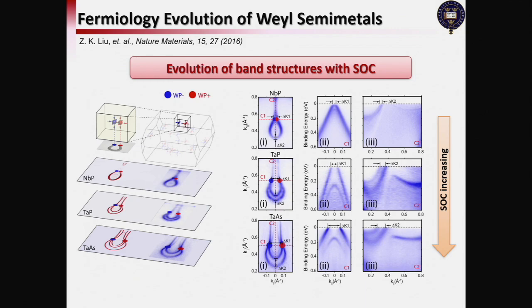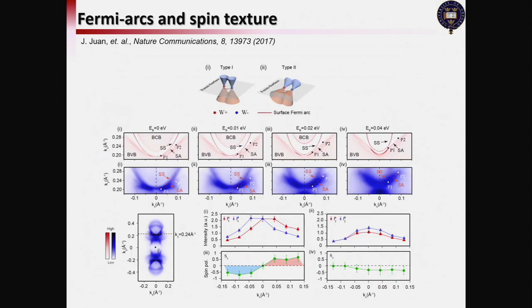And of course, then we can study how to separate the Weyl points, and that's essentially determined by the strength of the spin orbit coupling. This is the whole family of materials. We can see the separation increases when the spin orbit coupling increases, from niobium phosphide to tantalum phosphide to tantalum arsenide. Well, later on, there's a second type.